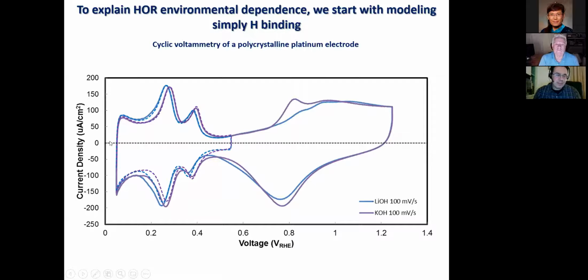That means I've hooked it up to a device that has the ability to pull electrons out of that electrode, therefore making electrons in the electrode more stable because I'm pulling negative charge out. They're now interacting with a positively charged surface. So now that's driving electrons to go from my solution into my electrode. And what I'll see is that I get a current, and this current must be generating electrons into my circuit. And I see some peaks in that current, and that's going to be indicative of the type of chemistry occurring on platinum. And I cycle positive, and I see a bunch of peaks associated with something that must be creating electrons that are going into the platinum surface and then into the circuit. And then if I go back and scan in the opposite direction, I see something that looks kind of like a mirror image across this x-axis, which is the reductive current when I undo all of those processes in the opposite direction and consume electrons.